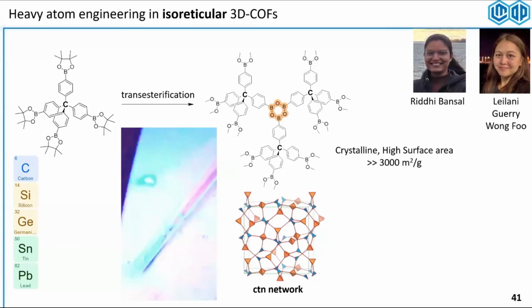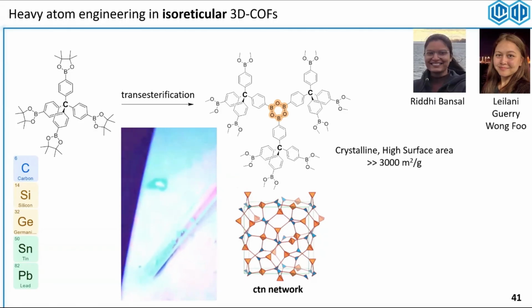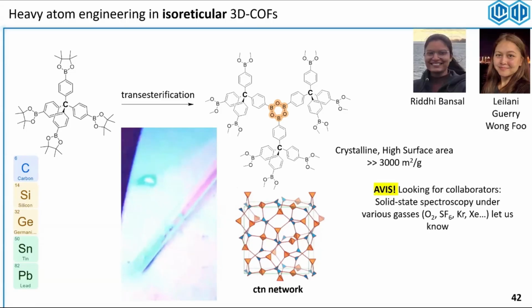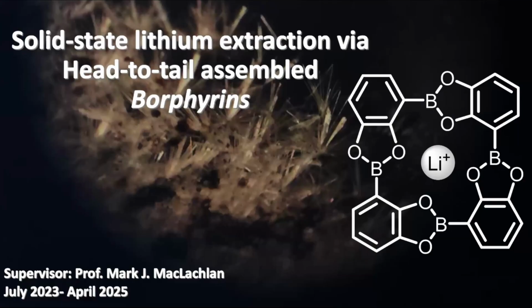So germanium is here in the center, as well as a tin-based COF, and the silicon and carbon, obviously. And we found that one of the COFs, so this is the result from last week, we don't have the full spectra yet, but it clearly has phosphorescence at room temperature, but under high vacuum. I have to put it in an EPR tube and suck the air out of the tube to be able to see the phosphorescence ever so slightly. So we are now looking for collaborators. That's why I presented this slide. Anyone who has a solid state spectrometer where we can infuse different gases into the system, I'm very interested to work with and study these in more detail, especially working on xenon and krypton. If you know anyone around, just send me there. And this kind of wraps up the PhD work that I had.